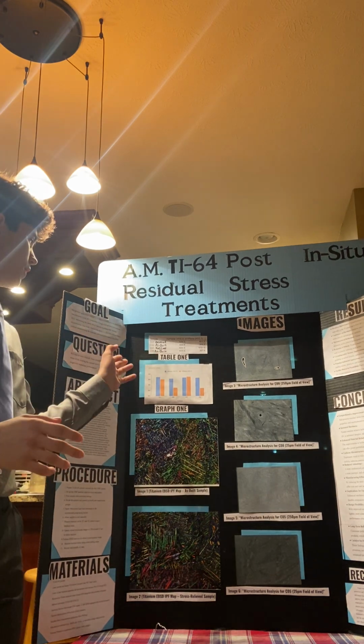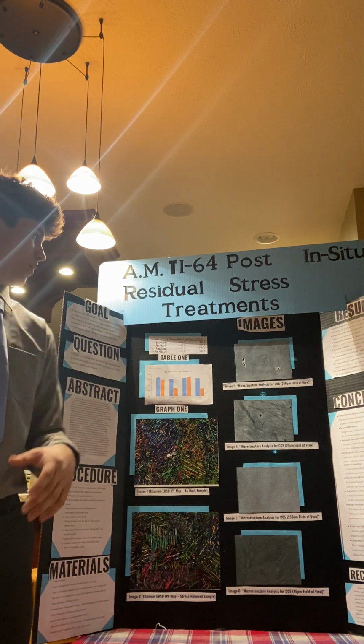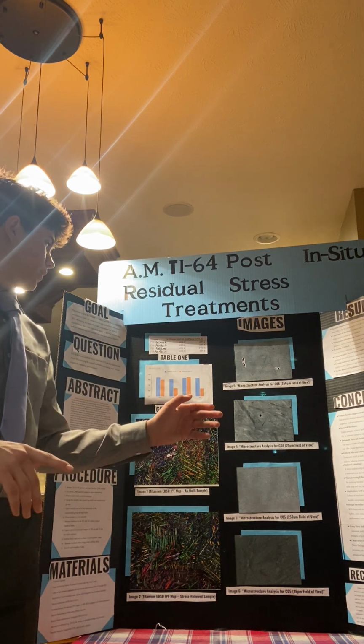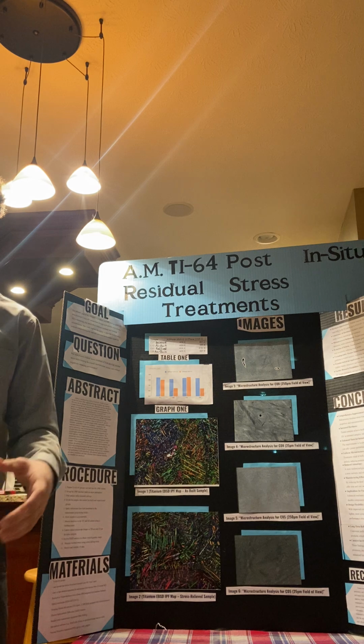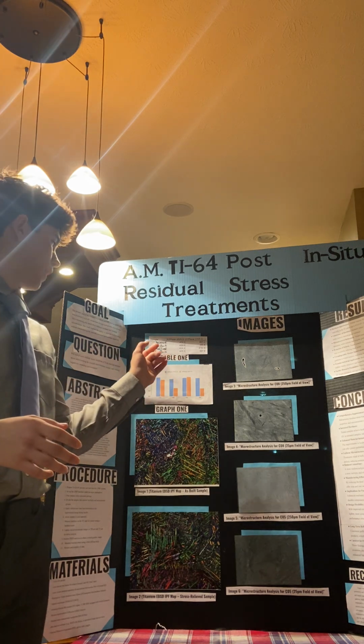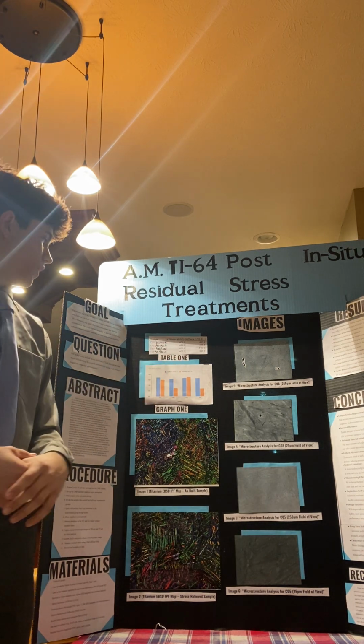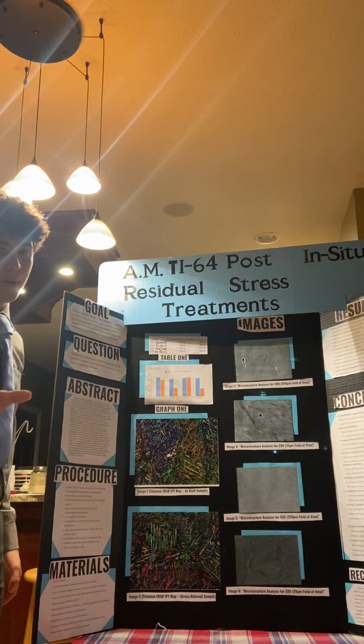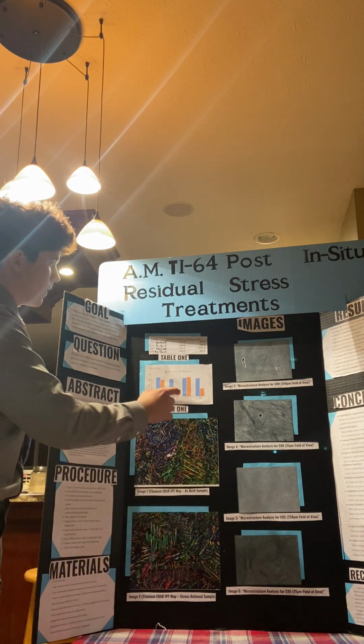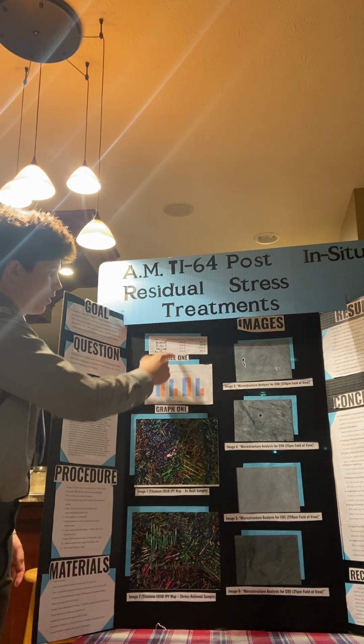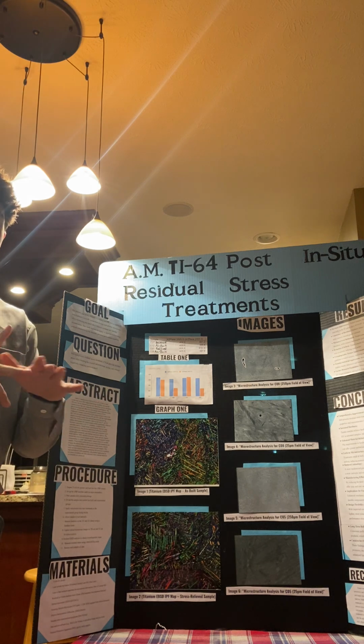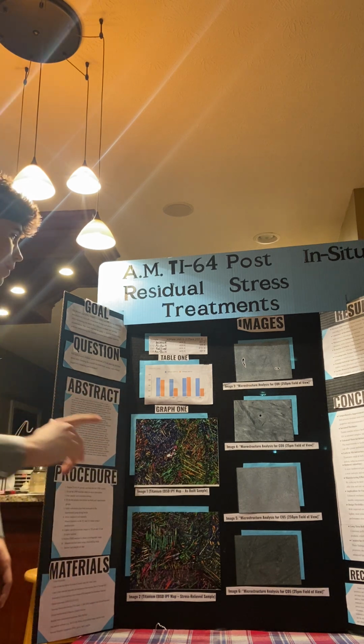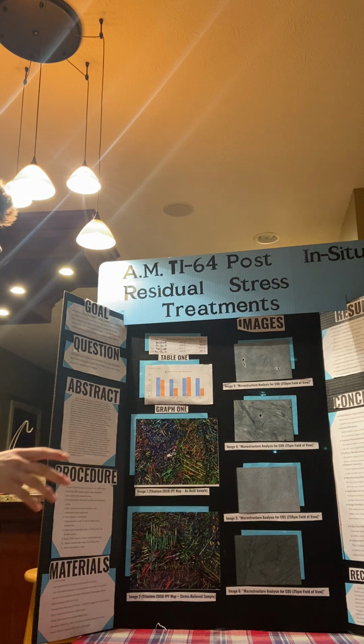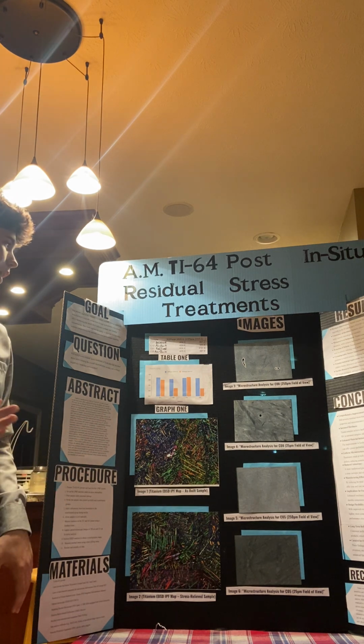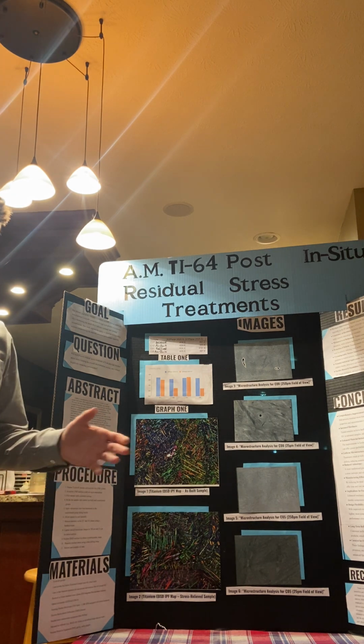We have CO5 and CO8 here. So CO5 was another experimental group with the XY plane, and CO8 was as built, the control group, with the XY plane. It's just the samples, and then we cut each of them in half. And so if you can look at the table here, which I have in my paper as well for future referencing. So with the XZ plane, you can imagine as you're building up, I didn't expect to see any change in any of these planes, but they're all relatively the same, varying from 404 to 410, which isn't very big of a difference in the Vickers hardness scale.